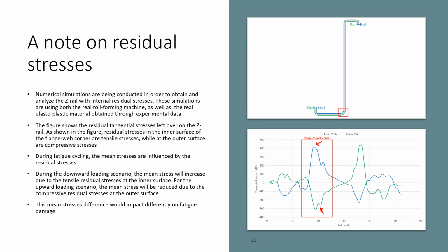It means that when I load the profile through the top, like so, our downward loading scenario, we have tensile stresses on the profile's corner that are going to add up to the already existing tensile residual stresses. If, on the other hand, I load the profile through the bottom, the tensile stresses are going to add up with the compressive residual stresses left over. So this means that loading the profile from the top is actually a more aggressive scenario than loading it from the bottom.